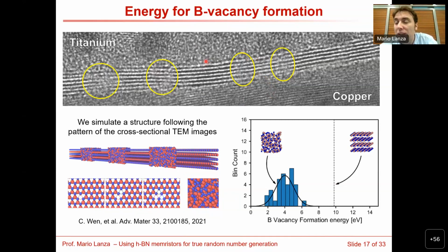For top view TEM images, some scientists have published chemical images with atomic scale resolution in single layer. But here we have multilayer and cross-sectional view. What we are seeing here is 40 nanometers thick. So in one single position, there are atoms of boron, nitrogen, and probably also from the electrodes. So that's the first difficulty, why nanochemical analyses are so difficult in this type of sample.